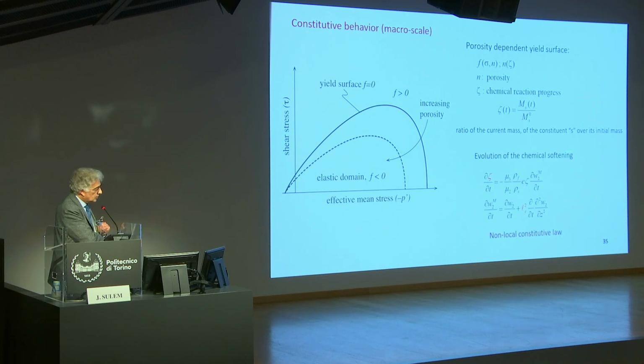And when we go to the constitutive behavior at the macro scale, where we write a porosity-dependent yield surface, the porosity will evolve with the evolution of the chemical reaction. So at the end, going through the derivation, what we obtain is actually a non-local constitutive law, because here the hardening parameter, which is a chemical reaction progress, will depend on the second gradient of the evolution of the dissolution product. So this is how the yield surface is shrinking because of the increasing porosity or because of the development of the chemical reaction process.